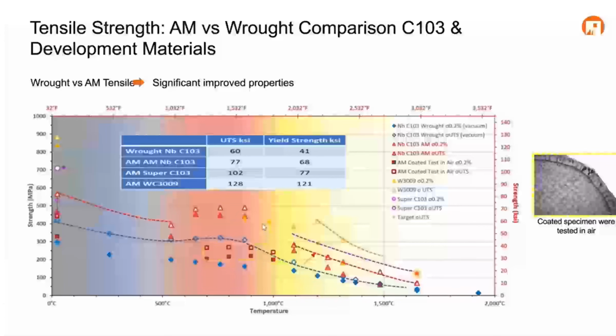And tested in vacuum, we're seeing much higher performance, as shown in the last slide. And then WC3009, with the added hafnium content, is a higher performance alloy even at much higher temperatures. What's important here is that even with some of our applications going up to 3000 degrees Fahrenheit, we're still seeing measurable benefits to the additively manufactured material, which is really exciting.